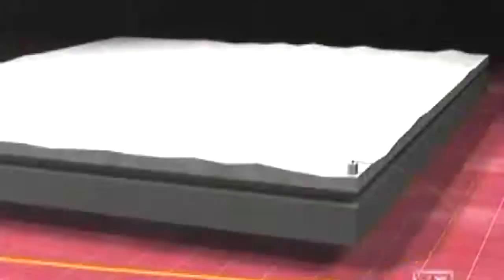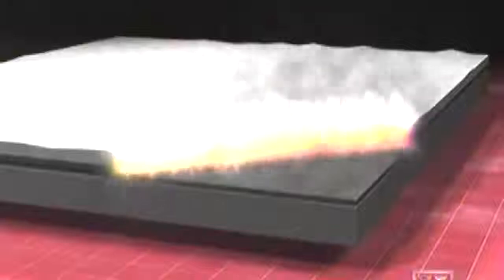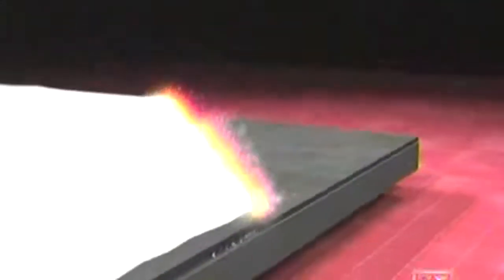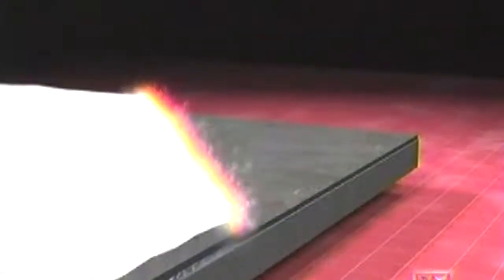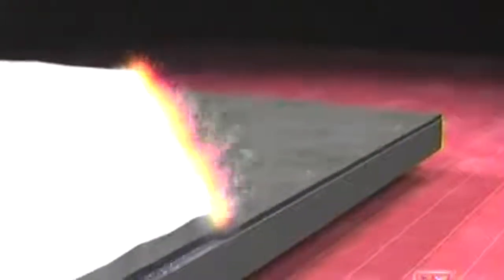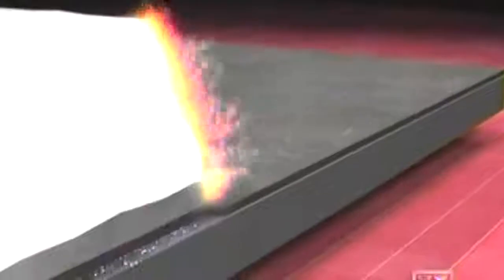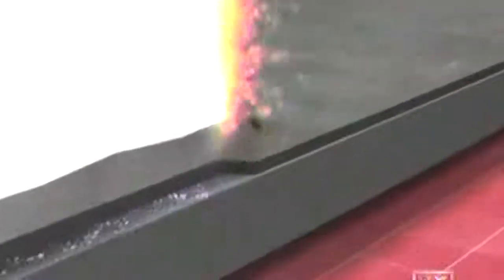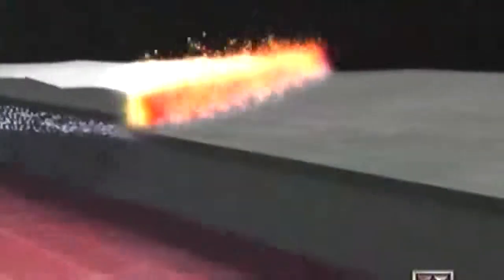The explosion is detonated from one edge of the cladder and moves across the upper level of the pack at a uniform speed. This explosive front progressively drives the cladder plate downward toward the backer at the slight collision angle caused by the standoff gap. Forward of the collision point, air is forced out of the gap at high velocity. All oxides and impurities are expelled, rendering the plate surfaces metallurgically pure and ideal for a weld.